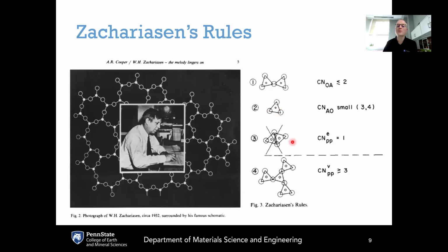Now, Zachariasen's 3rd rule is that these polyhedra share corners with each other. Note here, this is a corner sharing between 2 corners of these 2 triangles. They do not share edges, and they do not share faces. So this representation shown here has these 2 triangles sharing edges with each other, and that is prohibited because that would create a structure which is too compact, and this would lead toward crystallization.